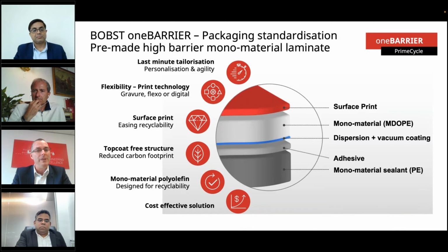And by removing the ink layer from the embedded structure, it has also helped Bobst and our partners to really maximize the barrier performance of the packaging structure. And additionally, any limitation on laminate bond strength related to the embedded ink layer has now been removed, so we can get higher laminate bond strengths, which is key for these sustainable solutions.